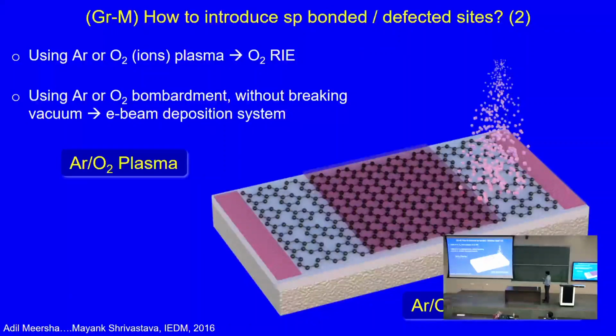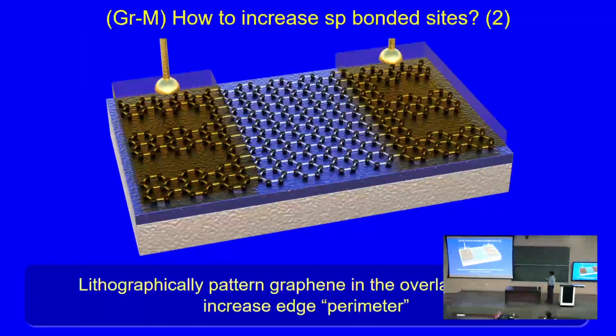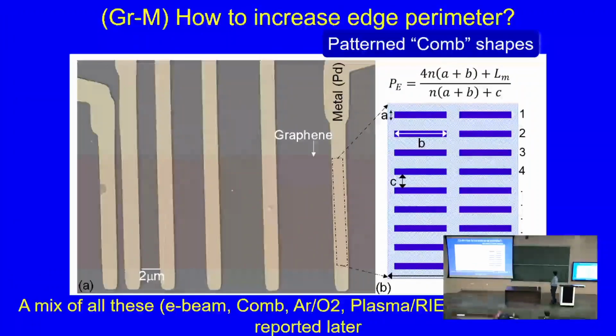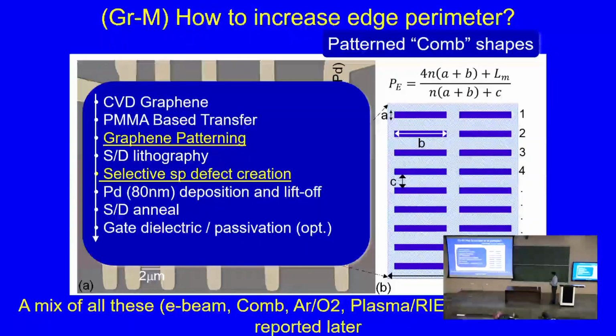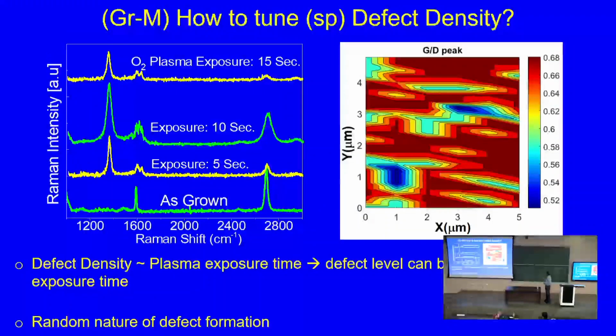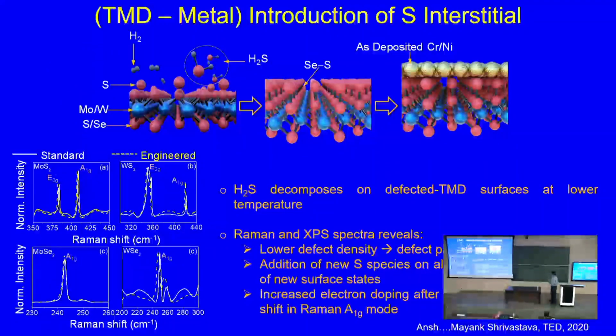Second was, you open this contact area, then we used either oxygen plasma or argon plasma to create these local damage sites, or we also created these patterns. So these are all lithographically patterned sites. These are all backgated transistors, where we created different variations. This is the contact area, and you see these small patterned sites, and we played with the dimensions of these patterned sites. As you increase the plasma exposure time, you see the defect density going up, confirming that we are able to pattern and create those carbon vacancies.